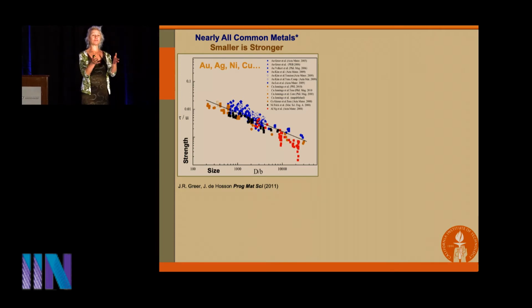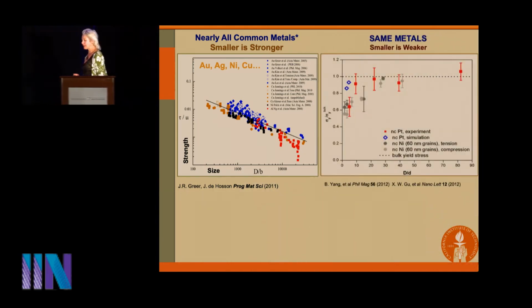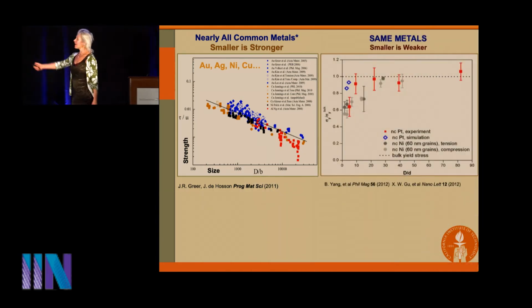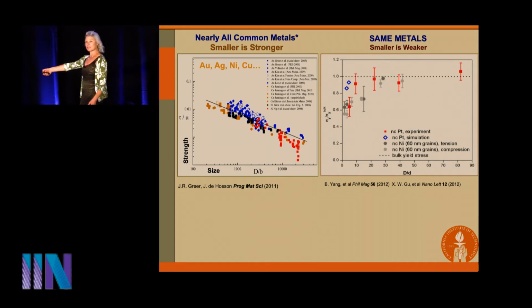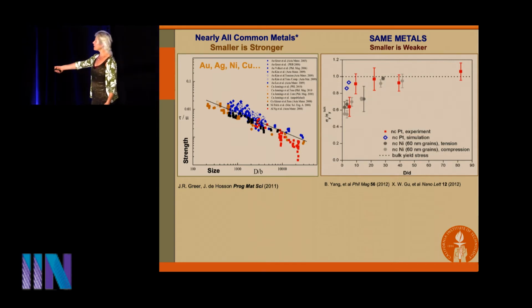What that means is that if you look at copper or take a gold earring, we know them to be very malleable, and if you reduce their dimensions to about 200 nanometers or so, the gold becomes as strong as steel. So smaller in this case is stronger. Now, take exactly the same metals and deposit them using different techniques, for example, sputtering or PECVD or all the nano deposition techniques that you are all familiar with. And all of a sudden, this effect is reversed. Now, smaller becomes weaker.